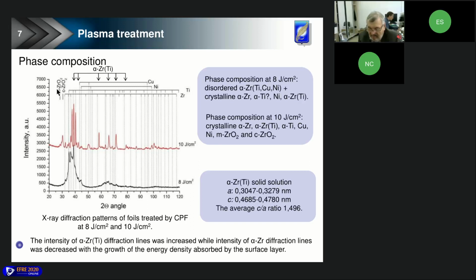Again, lattice parameters of the zirconium-titanium solid solution were calculated. You can see them on the slide. The strangest thing was that the average C/A ratio was equal to 1.496, much less than for zirconium and titanium. It should be noted that the C lattice parameter value appeared too small for the zirconium lattice and was slightly greater than that of the alpha titanium lattice. This can be explained either by the presence of tensile residual stress inside the lattice along the C direction, or maybe by preferential occupation of atomic inner positions in the hexagonal zirconium lattice by titanium atoms.